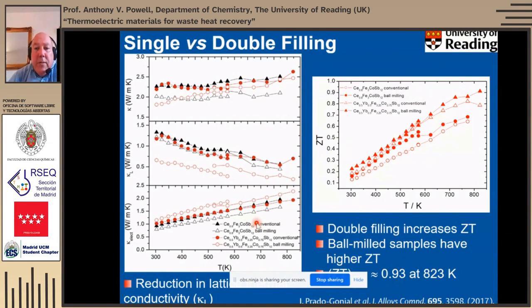So that was what we set out to achieve, and that's then reflected in the ZT values here, because we can see, unfortunately, we've now changed our symbols. So now the double filled are the triangles, and we can see that the performance of the triangles, whether made by conventional processes or by ball milling, is significantly improved over that of the single filled materials, and we get a maximum ZT of about 0.93 at 823 Kelvin. So that seemed to vindicate the strategy of saying, well, what happens if we use more than one filler, and we aim to introduce ions, rattlers, with different vibrational frequencies? It does indeed give improved performance.